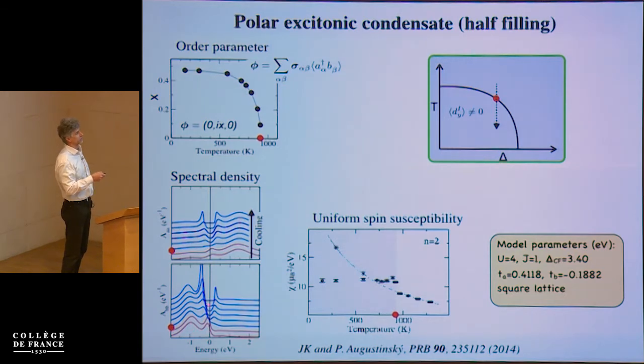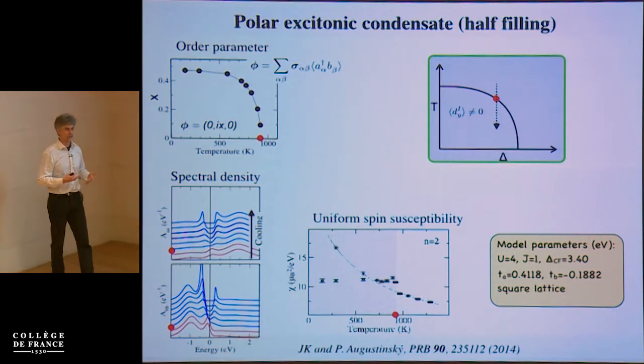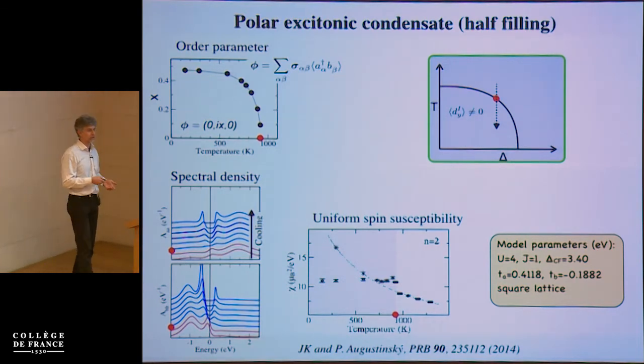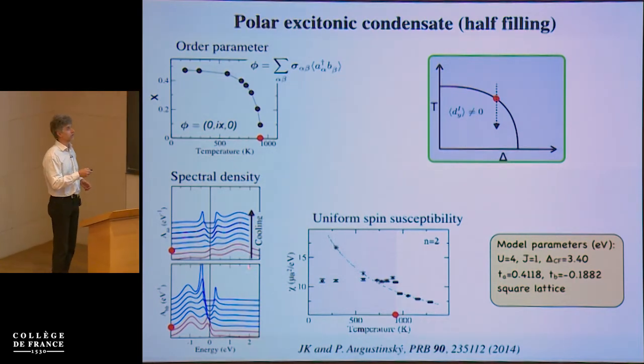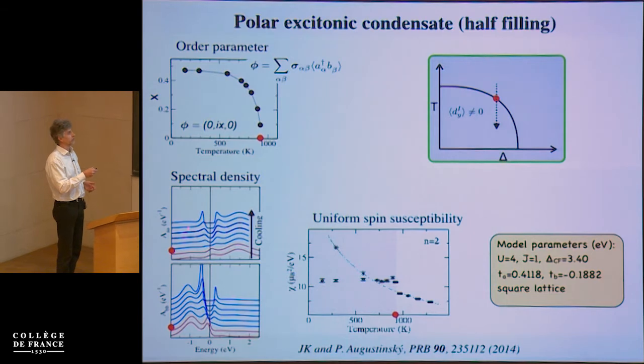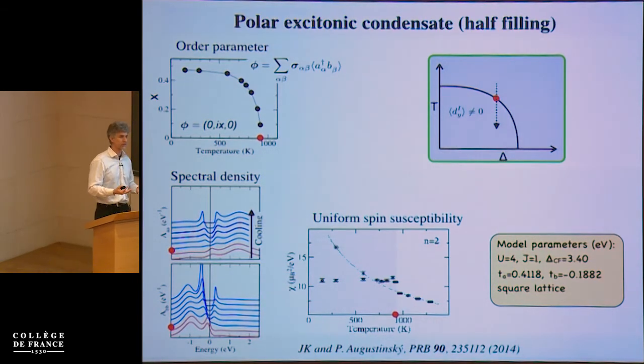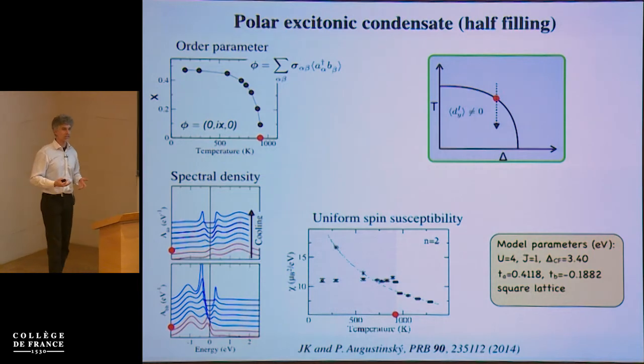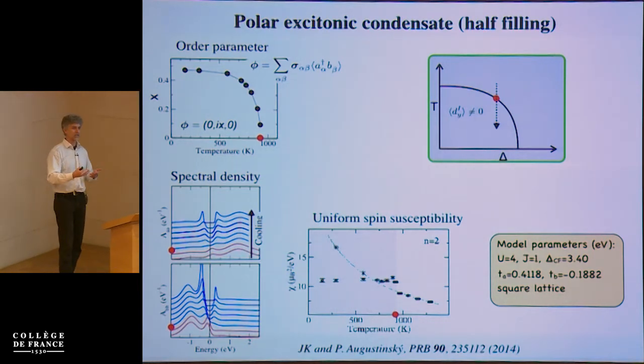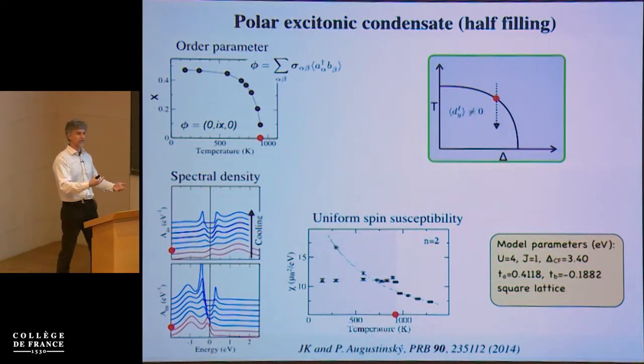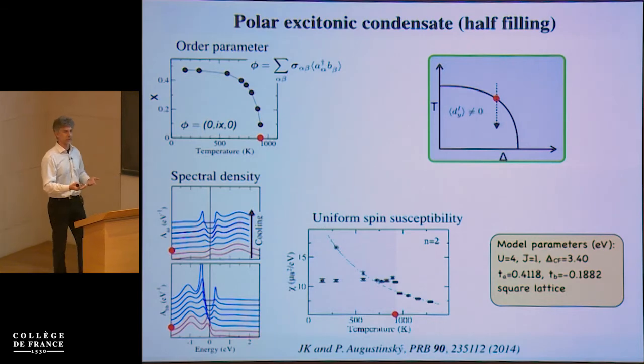And as we go into the condensed phase, a gap opens. And if you're familiar with S-wave BCS superconductivity, this should look quite familiar. You have a 1-particle gap with these peaks, which in superconductivity are called Hebel-Slichter peaks. And this is indeed no coincidence. There is essentially an exact mapping between this excitonic condensation and superconducting transition.